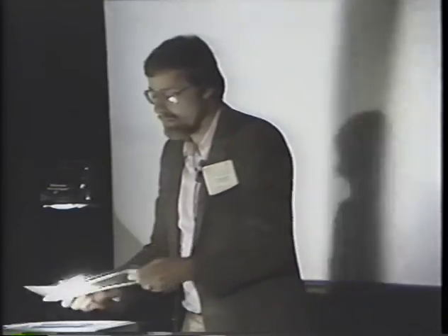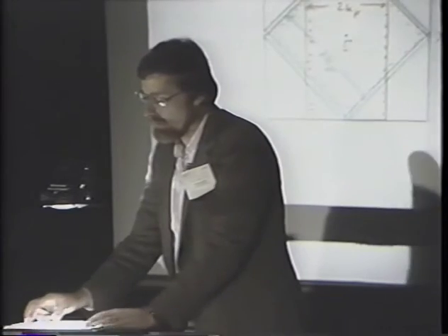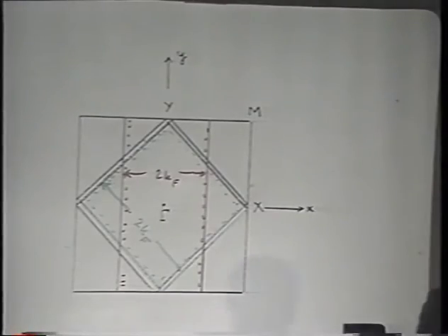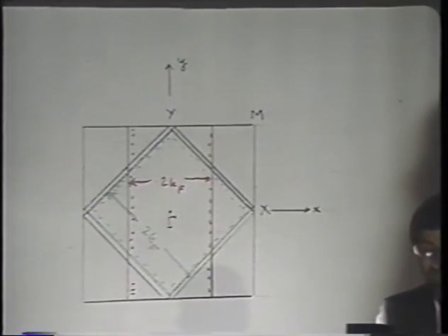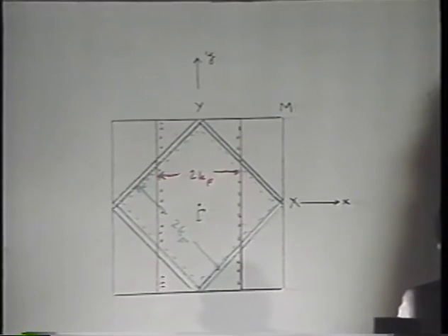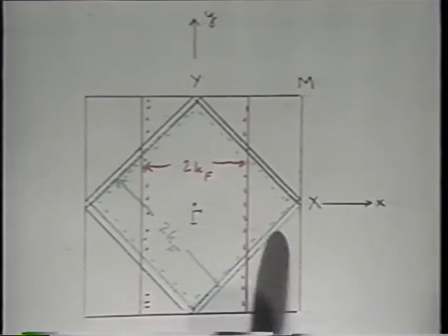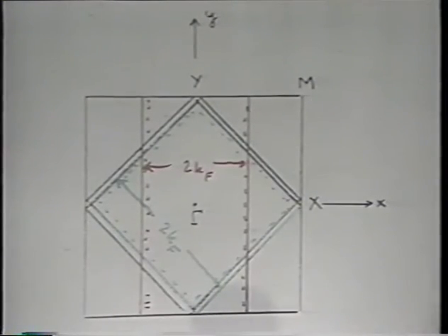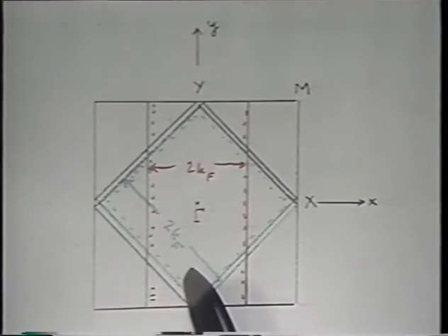Now, if you look at the Fermi surface of this material, then you find a rather remarkable Fermi surface. The two-dimensional bands give you cylinder-type Fermi surfaces, but in addition to being cylinders, they are rectangular, and this has remarkable properties. The same Fermi wave vector spans many pieces in k-space. This, by the way, results from those sheets. In addition to this feature, we have the chains.